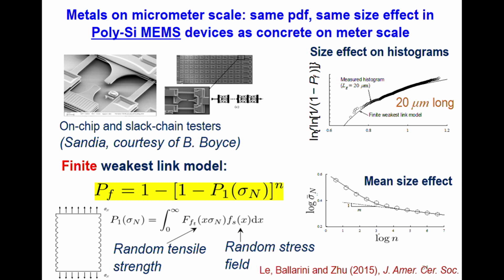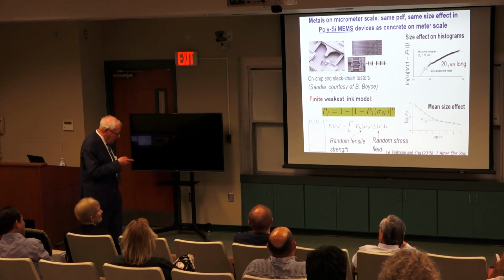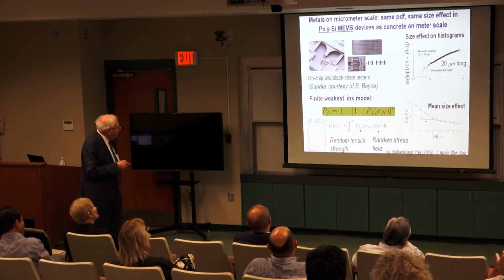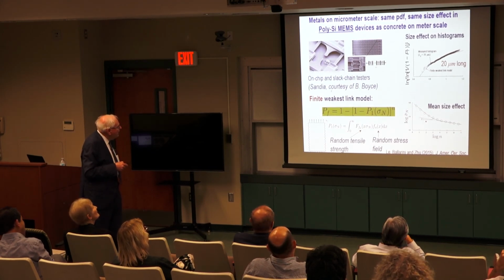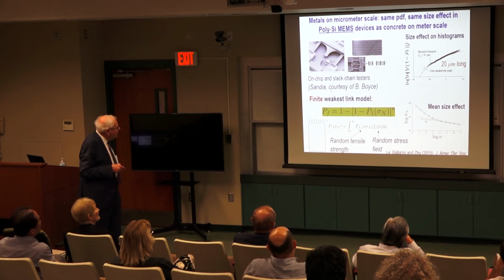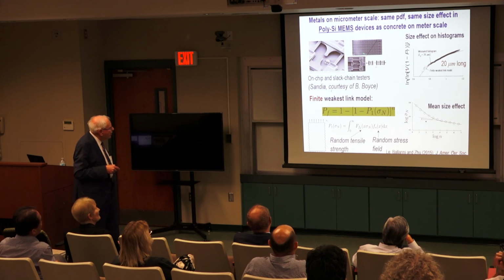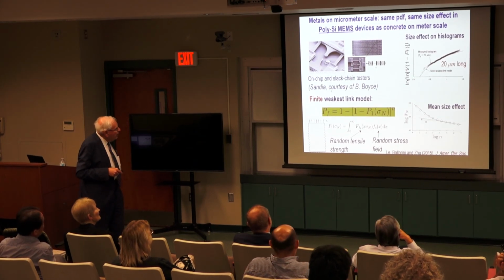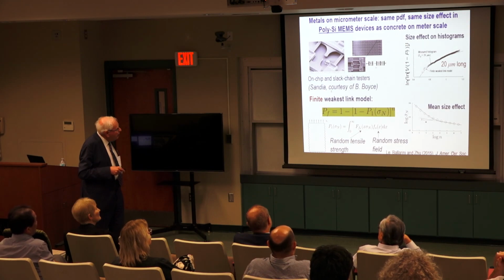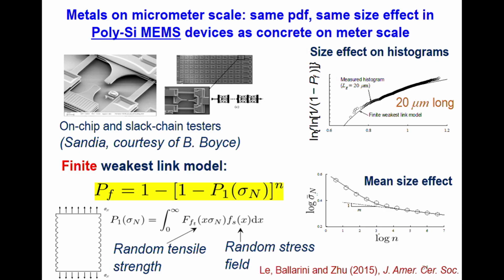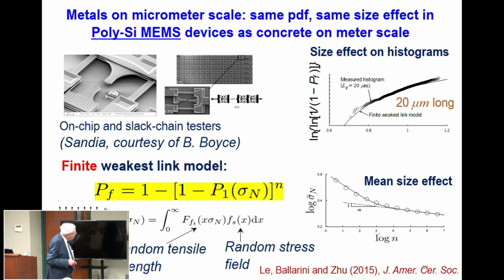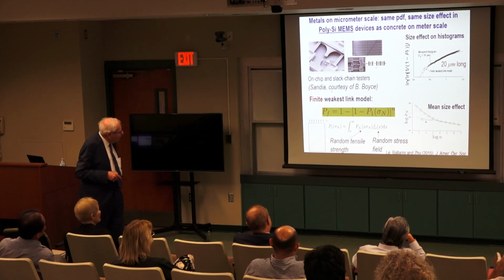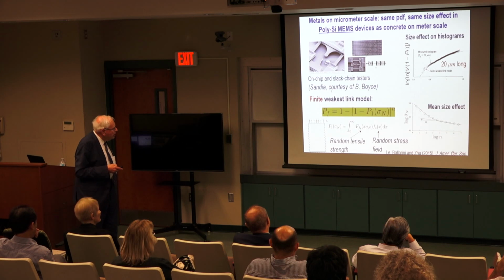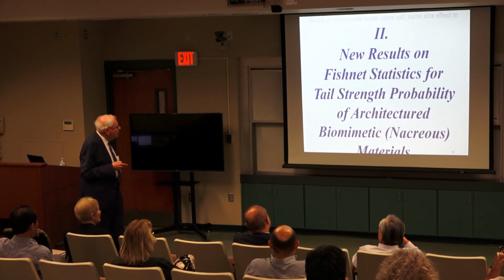My former student, Jia-Liang Le, who is in Minnesota teaching as associate professor, tested at Sandia with Boyce similar problems for polysilicon on the MEMS scale. They use a chain slack tester, which is generally used for this, testing many specimens on loading. You see again the same behavior. In Weibull scale, you don't get a straight line, you get a curve. That's verified here. And they tested size effect, and this size effect is shown here. It's not a straight line like with Weibull, it's a curve. So in actually a micrometer scale, every material is quasibrittle.